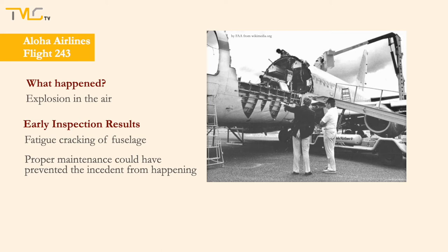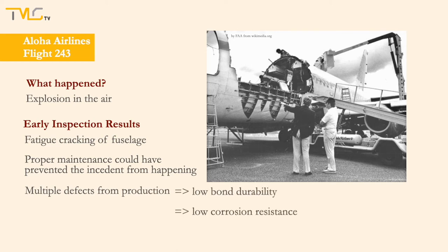The cold-bonded lap joints were discovered to have multiple defects from the early production stages, causing low bond durability and low corrosion resistance, exacerbating multiple-site premature fatigue cracking and leading to the fuselage failure initiated at the lap joints.